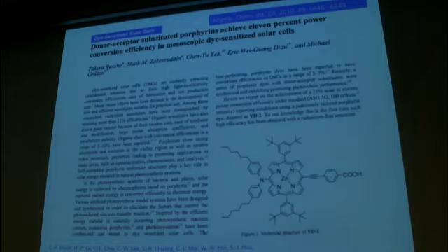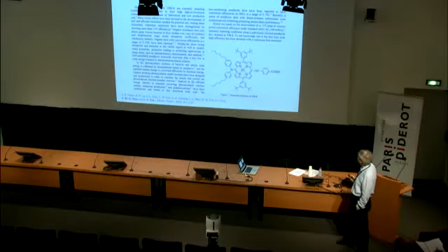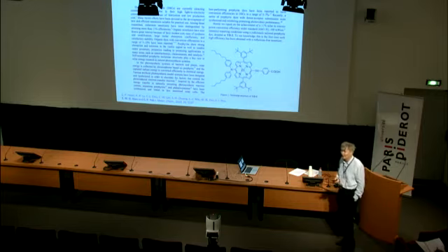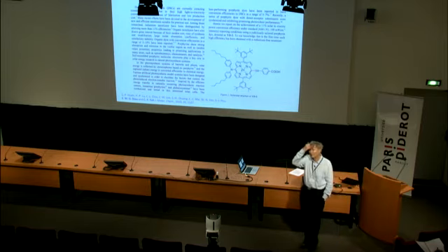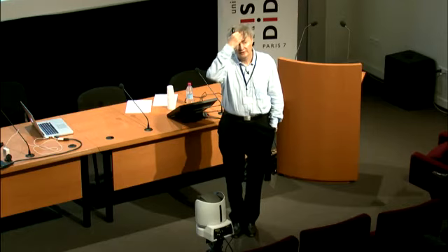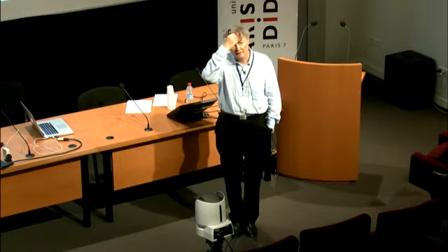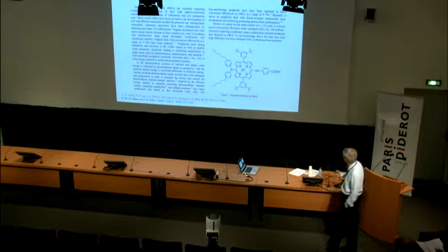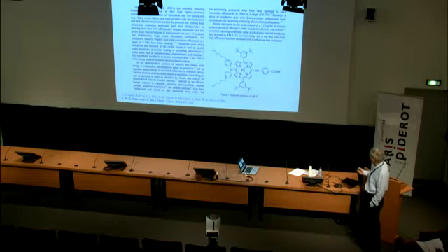They made a D-pi-A dye with the porphyrin now being the bridging part, and this has given them remarkable efficiency with the iodide/triiodide, over 11%. So that was for a while the highest efficiency one could achieve with a non-ruthenium dye. It's a metal complex, but it doesn't have ruthenium in it. It's a zinc complex. And so you have the donor, the pi bridge, and the acceptor.